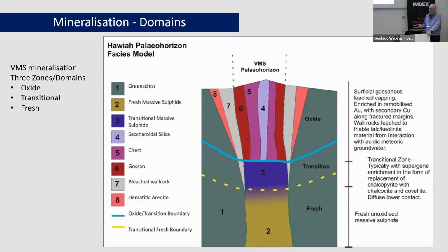One of the things they found with mineralogy here when it was originally studied is that the gold is less than probably 1 micron. So even in the oxide horizon, you have to grind to 30 microns to be able to have a chance to expose the gold for leaching. So it's actually a problematic ore even in the oxides. Supergene it's pretty tricky as well. Probably you get reasonable flotation response. It's much higher grade than the fresh sulfides below it, but again quite tricky and not very thick. So each of these tonnages, that's 20 metres, that's probably 10 to 15 metres, and then this thing goes down and it's relatively open at depth.